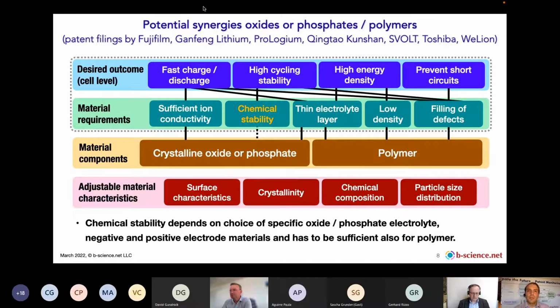And so here we attempted to visualize and rationalize why the combination of oxides or phosphates, ceramics with polymers can make sense, because if one takes the desired outcome performance aspects of fast charge discharge, high cycling stability, high energy density, and the prevention of short circuits, these can be connected, for example, to sufficient ion conductivity in terms of fast charge discharge, which then certainly is an advantage of oxides or phosphates as compared to polymers.